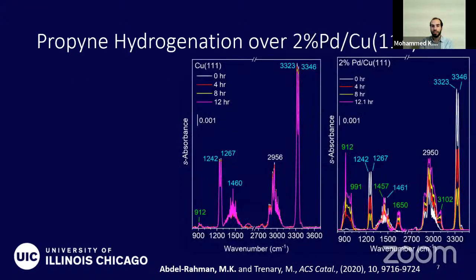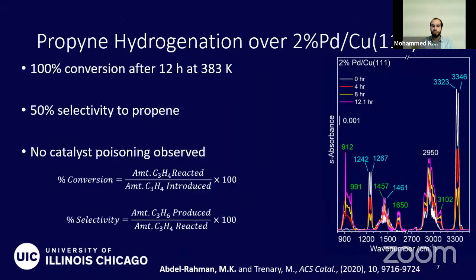But when we contrast this to a 2% single atom alloy, we see that within the same 12-hour period, we have complete reaction of propyne. So here the intensity of the white spectrum was propyne at 0 hours, and the pink one being after 12 hours. So after 12 hours, basically we've converted all of our propyne. However, when we look at the conversion and the selectivity, we find that we have 100% conversion, but 50% selectivity. So although we have these significant peaks here, 912, 991, and so on for propylene, it only accounts for 50% of the starting material.